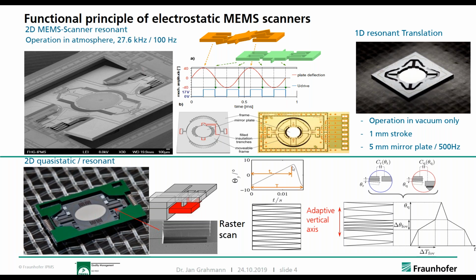So for the outer axis, we can have a linear movement, for example. And for the inner axis, we can have a resonant movement, so that you have a linear movement in vertical direction, for example, and a sinusoidal movement of the scanner in horizontal direction. Another possibility that this quasi-static actuation enables is shown here. For example, we can vary the line width in such a 2D scanner by adjusting the speed of the scan trajectory of the quasi-static axis. So you go faster here, so you have a larger line width, and you can drive it slower here, and the line width, by constant oscillation of the resonant axis, becomes more narrow or more tight.